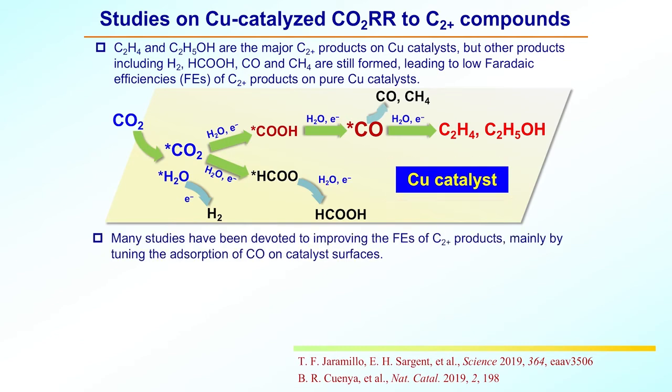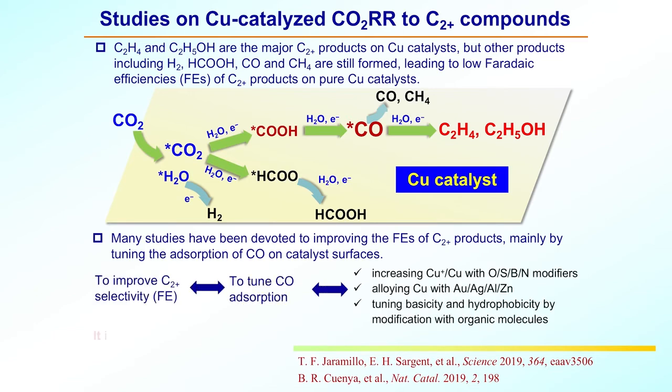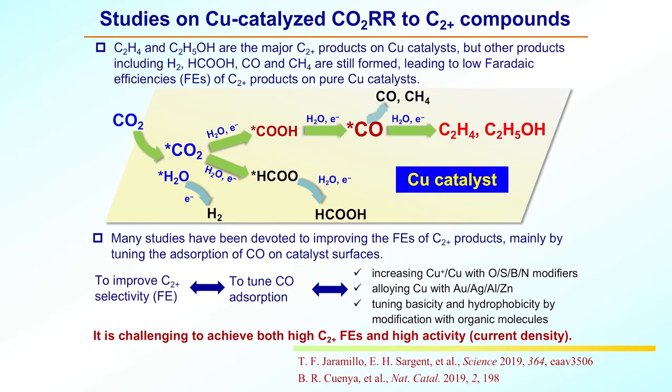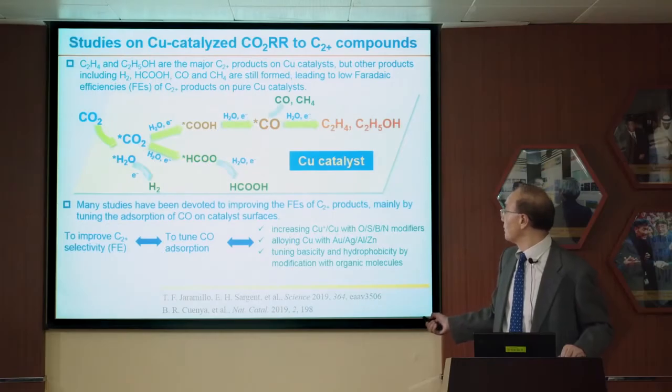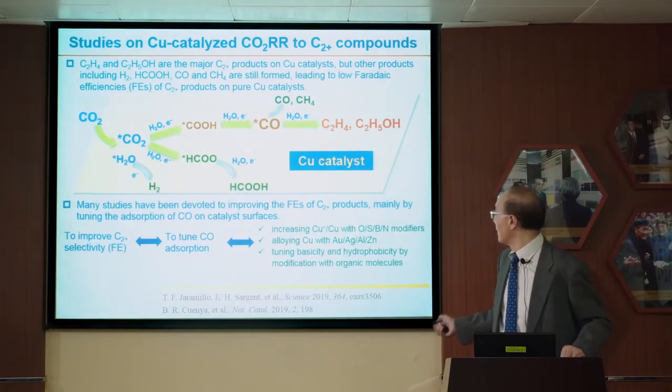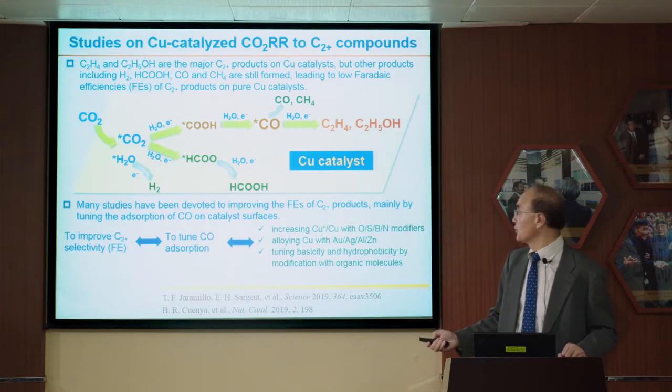So many studies have been devoted to improving the Faradaic efficiency of C2+ products, many by tuning the adsorption of CO on catalyst surfaces by, for example, increasing the ratio of Cu+ to Cu0 with some anion modifiers, by alloying copper with gold, silver, aluminum, and zinc, and by tuning basicity and hydrophobicity by modification with organic molecules.